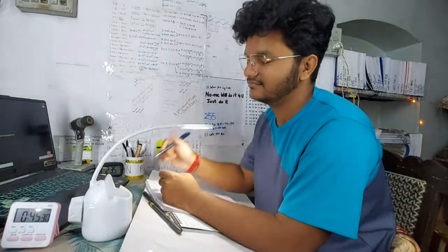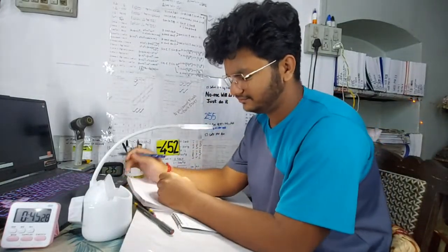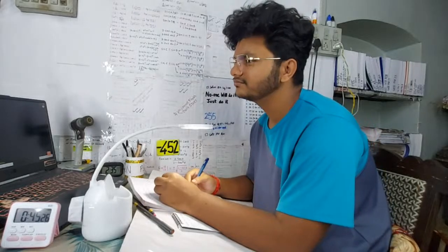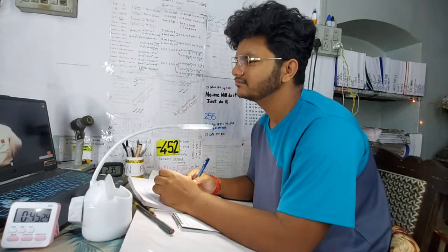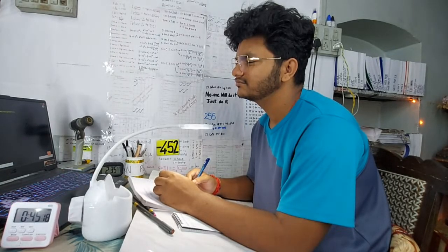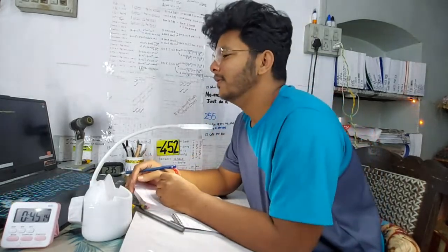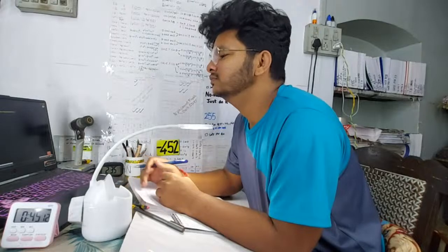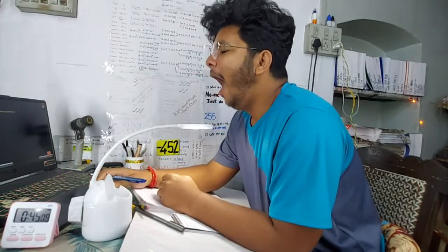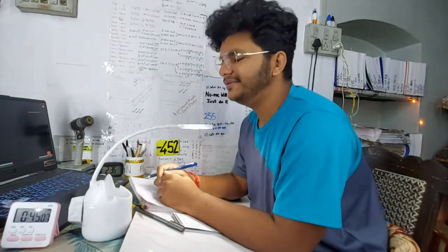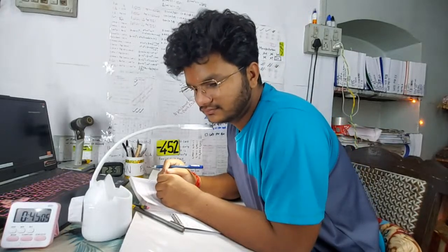At a temperature below A1, after rapid cooling, we will hold it at a constant temperature, right? And then we will find out the beginning time of transformation and the ending time of transformation at this temperature. So I write B1, E1. From above A1, let us say we have rapidly cooled it to something like 700 degrees centigrade, below A1, and then it is held at the constant temperature for a sufficiently long period of time.